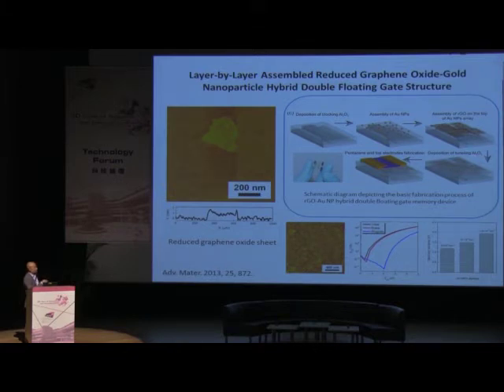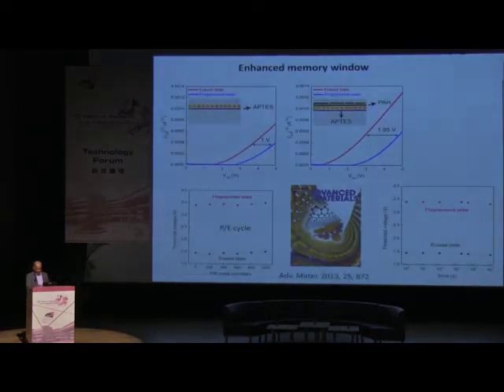And finally, we have a tunneling aluminum oxide and the semiconductor. As a whole, the device looks like what you see here. And we used a saturated density of nanoparticles so that the memory data storage must be much higher. And you can see the difference, with and without graphene. Here you have graphene, and you can see twice the memory window.